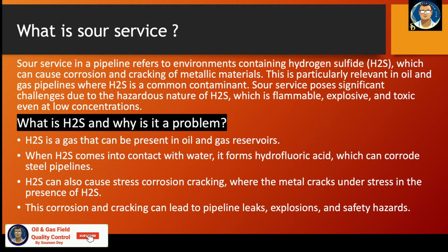Sour service in a pipeline refers to the environments containing hydrogen sulfide, which can cause corrosion and cracking to the metallic material. This is particularly relevant in oil and gas pipelines where H2S is a common contaminant. Sour service poses significant challenges due to the hazardous nature of hydrogen sulfide, which is inflammable, explosive, and toxic even at low concentrations. What is H2S and why is it a problem?